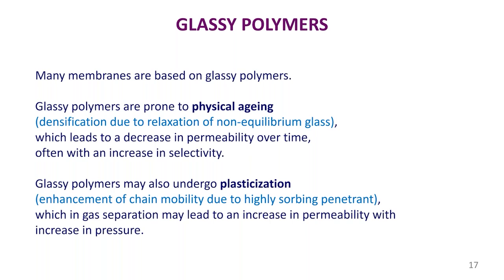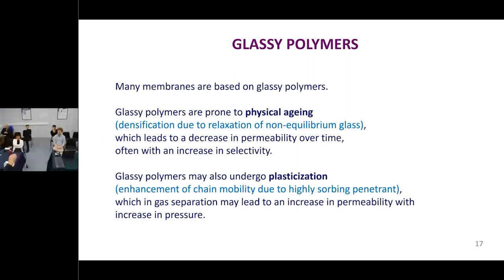And so in practice, where plasticization occurs, what you tend to see is as the pressure that you apply to the feed increases, you start to get an increase in permeability and a loss of selectivity. And you also find that if you study a single gas on its own, which is what we often do in the laboratory because it's easy, everything is different when you look at a real mixture, and often worse. And so plasticization is another thing that we really have to think about, understand, and control.